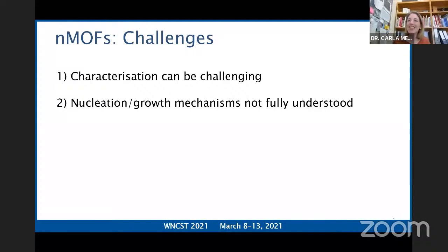Instead, I'm going to focus on that second challenge, which we think can be at least partially addressed through the use of a microemulsion-based synthesis. So at the very least, I hope I can show you today that we think microemulsion-based syntheses can provide some new insight into some of the potential growth pathways or growth mechanisms. And these can be revealed through a systematic approach of finely tuning the synthetic conditions in a way that we can do with a microemulsion-based synthesis that can't easily or necessarily be achieved using more conventional approaches.